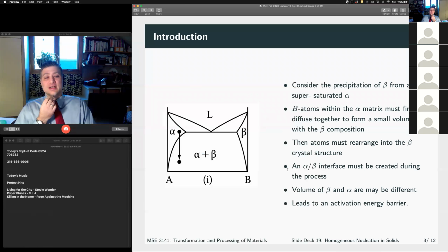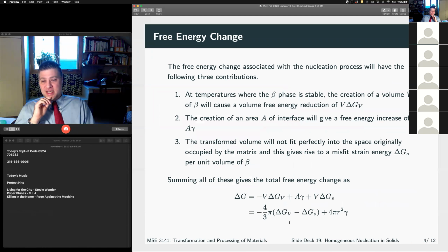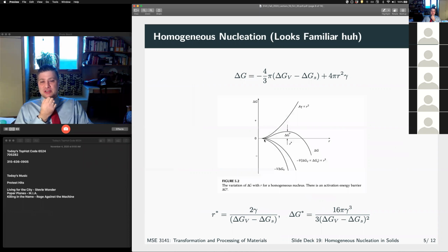The only crucial difference is we need to take account that solids have a volume misfit, right? Whereas a liquid or a vapor can flow easily under the shear stress, solids can't. They resist, right? They keep their shape. So we have to account for the volumetric strain, right? And that volumetric strain just reduces the driving force for the phase transformation, much like the surface energy reduces the driving force. And we need to account for that. But other than that, the theory is exactly the same.